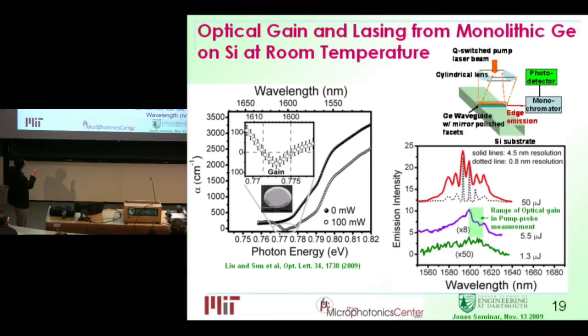And this is a regular absorption curve without pumping. And with pumping, you can see the absorption goes to negative. And this error bar is actually a very conservative estimate. So even with this most conservative estimate, you still get a negative absorption coefficient around 1605 nanometers. That means you're getting gain. So you're not absorbing, you're actually amplifying the light now. So in principle, you can do a laser with this disk, but the index of germanium is so large that light is very hard to escape out.